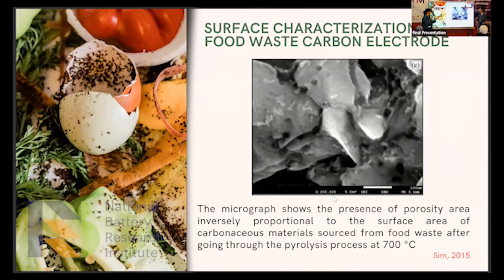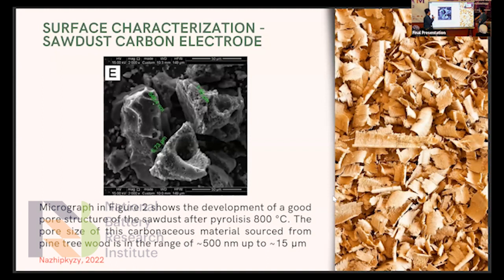Next, the picture shows a micrograph of the food waste carbon electrode. It shows a high porosity area after going through pyrolysis at 700 degrees Celsius. Here are our other micrograph pictures from the sawdust carbon electrode. It also shows a high porosity after going through pyrolysis at 800 degrees Celsius. So it leads to good ion mobility.